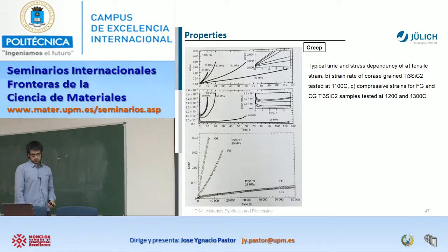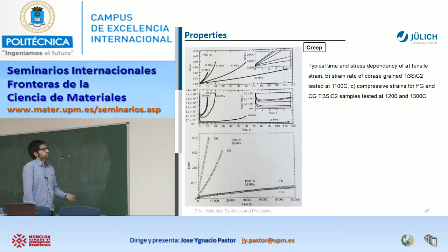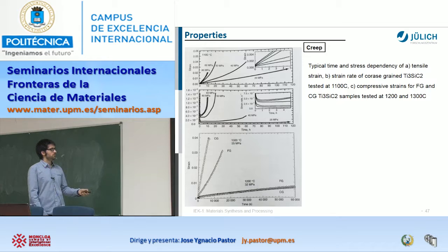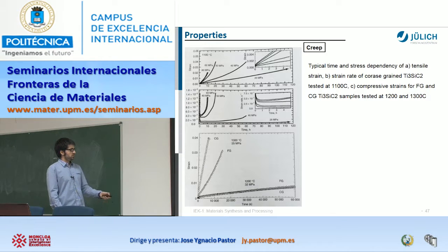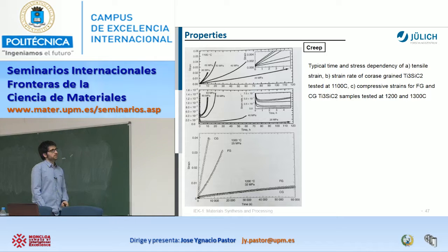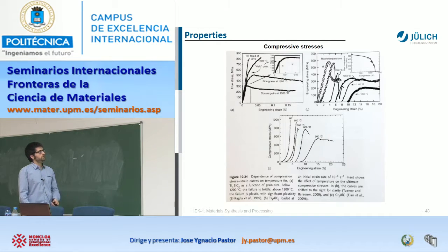And here, obviously, if we talk about temperature, creep is totally critical. If we want to use this material, this is not the case like the ultra high temperature ceramics that are for a few minutes or few seconds. This one is like a structural material, or that is the idea to use it. Creep is totally critical, and obviously depends on time, stress and temperature. And here are a few examples of how this evolves also as a function of coarser grains or finer grains or different materials. For example, at 1200 it's quite good, at 1300 it starts to be lower. It's just different values. Okay, I don't want to bother you with that.